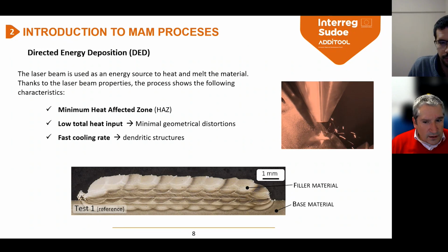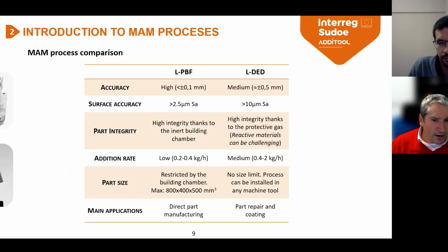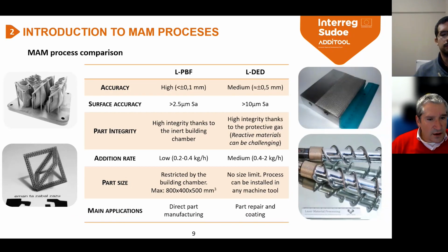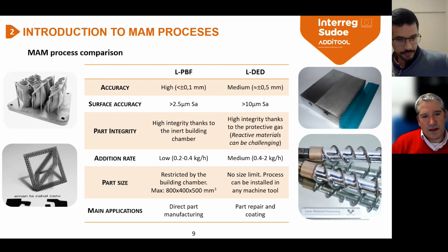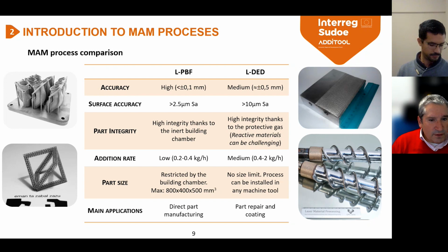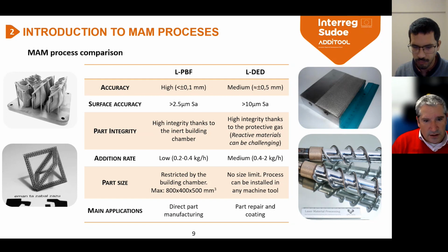So just to finish that, in comparison, here you can see both techniques. On the first hand, the laser powder bed fusion, we have a relatively good accuracy, considering that it's a thermal process with metal fusion. We can obtain parts below 0.1 millimeters, so it's quite good. Surface roughness is also quite good, below 2.5 microns of mean roughness, which some people could consider not very good quality, but if we consider that it's a thermal process, it's relatively good. We obtain very good integrity in the parts because of the inert gas chamber.